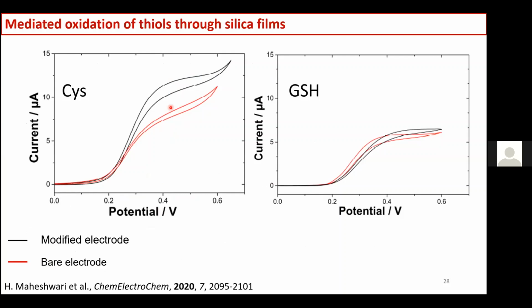showing that for cysteine the presence of the silica film was having an effect on the kinetics of the reaction, whereas in the case of the glutathione we had similar limiting current, suggesting that maybe the glutathione was not so bothered by the presence of the film, and so suggesting that maybe glutathione was not entering the pores to react with the ferrocene, but it was rather the ferrocenium that was diffusing outside to the bulk of the solution. And anyway, the kinetics was sufficiently slow for the glutathione not to be bothered by this extra diffusion, let's say, of the ferrocenium through the film.